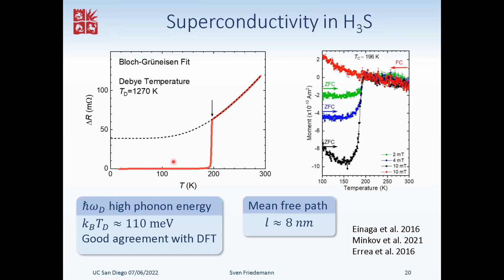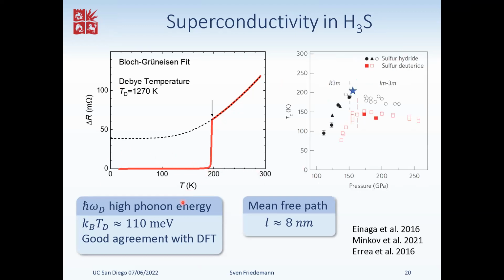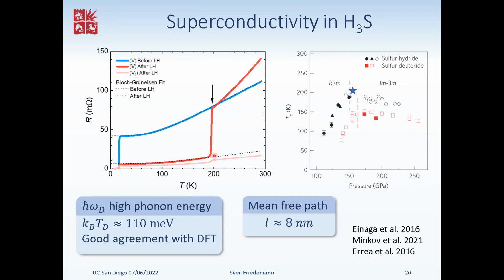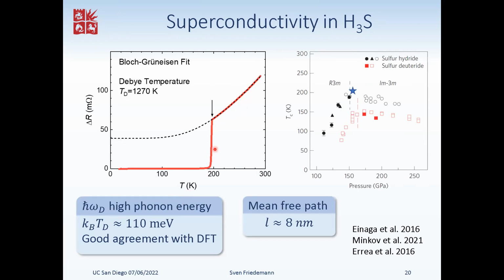So in the resistance measurement, I should be honest about this, we have subtracted a residual contribution from the sulfur. So we've not got the claim for zero resistance of the H3S phase in this particular sample. Eremets has got this claim. He has produced samples which showed, in his experimental resolution, zero resistance. You could then look at the noise of these experiments and extract essentially an upper limit for the potential residual resistance that's still in there, and that's of the order of nanoohm centimeters in his samples.